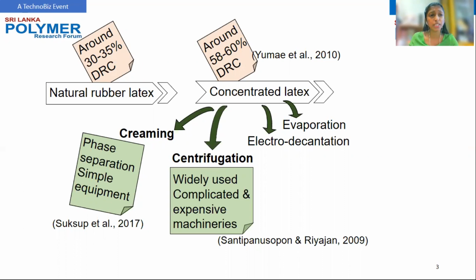Centrifuging is a widely used and well-known commercial process, but it needs complicated and sophisticated machineries and skilled people. But for creaming, a creaming agent called sodium alginate can be added into the field latex, and then the creamed rubber fraction and the serum are separated due to a gravitational field. So the creaming process requires simple equipment and low power consumption.